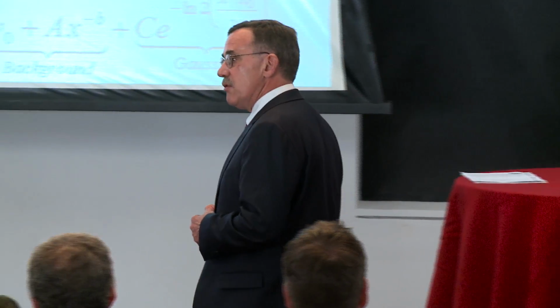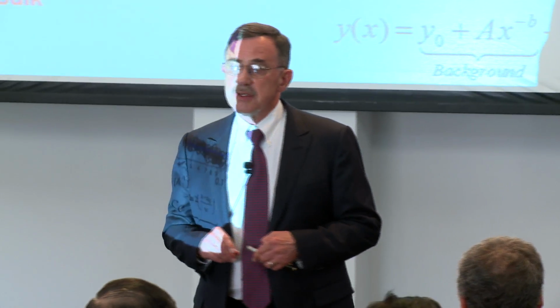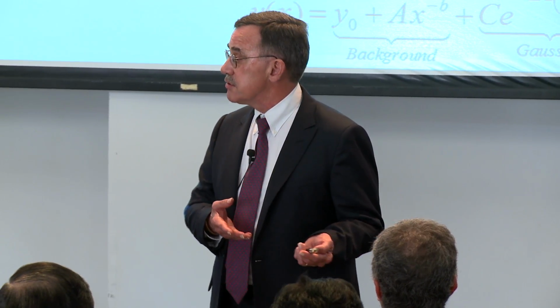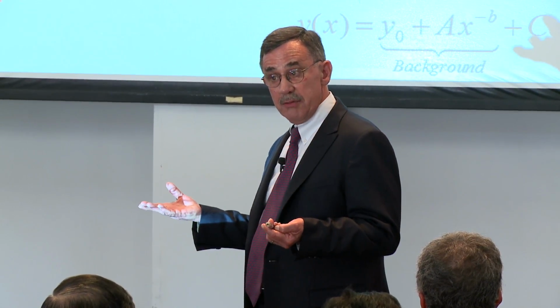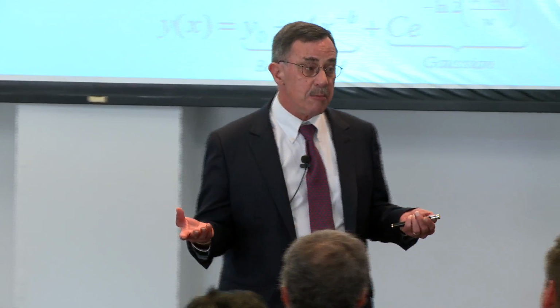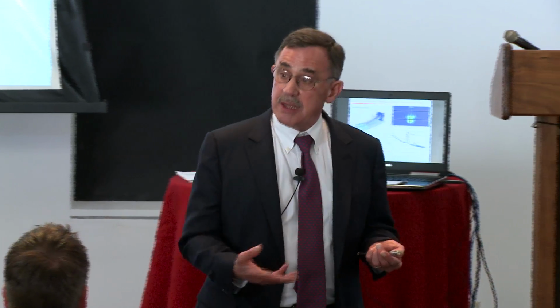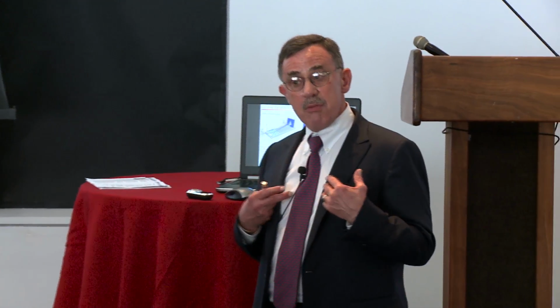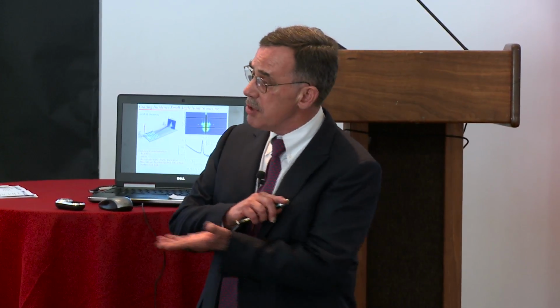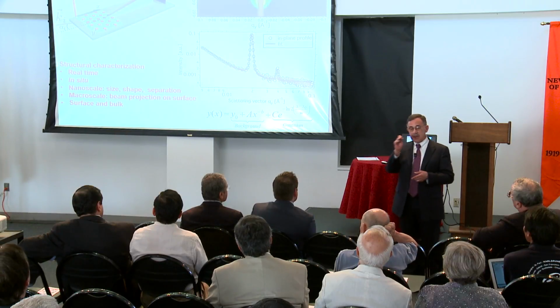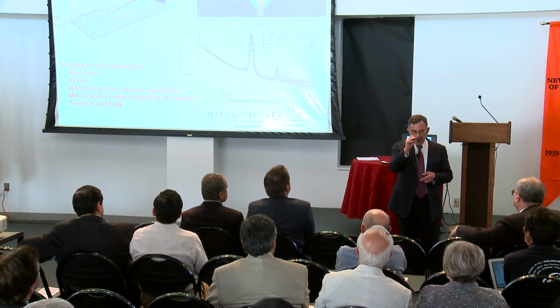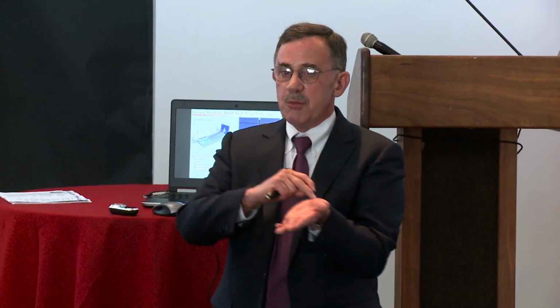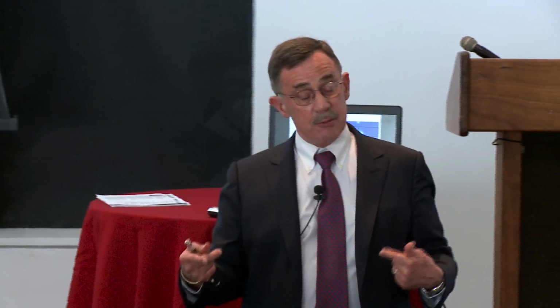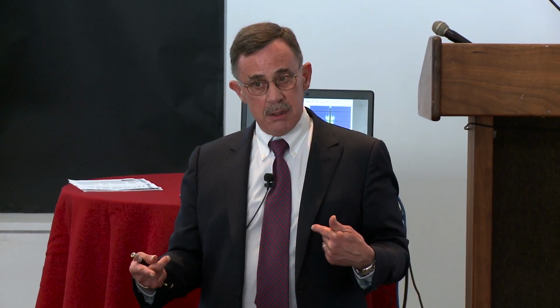When you think of nanoscopic level, you can think of scanning probe microscopy, or you can think of X-rays. Now, X-rays are great because they can characterize structures on the atomic level or the tens of nanometer level fairly straightforwardly. X-rays have a wavelength that may be 1.5 angstroms, a tenth of a nanometer, so it's commensurate with the size scale of the structures. But in order to probe a large area, we use what's called grazing incidence X-ray scattering. What that is, is we take an X-ray beam and bounce it off a surface. If you think of an X-ray beam that may be 3 micron in diameter, bouncing off a surface at a grazing angle, then we project the X-ray beam over a large area on the surface. And we can probe areas that are roughly about 1 inch in length with the X-ray beam. So we can characterize structures over large areas on the nanoscopic level.